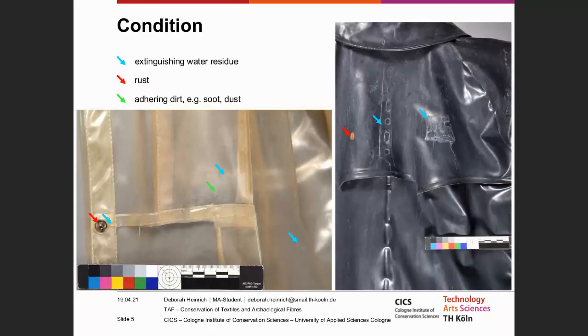The damage and soiling caused by the extinguishing water are shown on this slide in detailed illustrations. On the left, you can see a detail of the lady's coat. Since it is transparent, the whitish residues, which consist largely of the lime from the extinguishing water, are somewhat harder to see. The residues are marked by blue arrows. On the men's coat to the right, in contrast, it is clearly visible on the black film where the residues are and that their intensity and distribution varies.